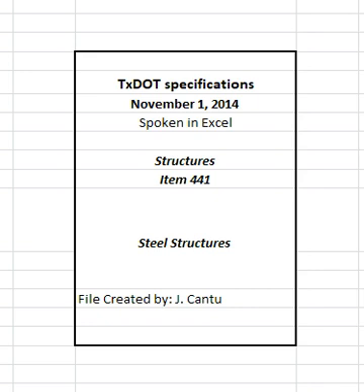3.8.3 Machine surfaces. Clean and coat machine finished surfaces that are in sliding contact, particularly pins and pinholes, with a non-drying, water-repellent grease-type material containing rust-inhibitive compounds. Ensure the coating material contains no ingredients that might damage the steel. Protect machine surfaces from abrasive blasting.